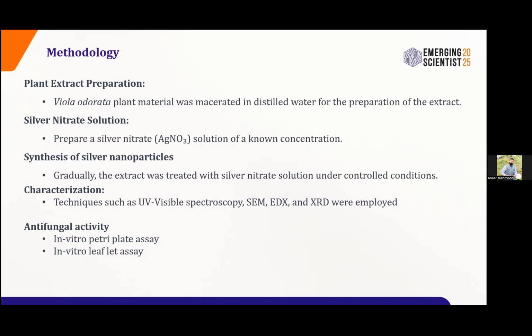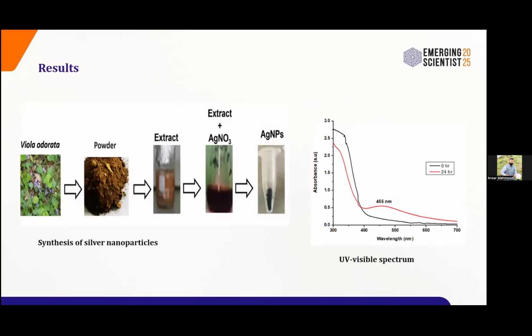The methodology I adopted for this research, first of all, was the plant extract preparation. The plant used for the preparation of nanoparticles was Viola odorata. The whole plant was ground into powder and an extract was made using distilled water, and then nanoparticles were synthesized by mixing the plant extract with silver nitrate solution under optimum conditions. They were characterized using different techniques like UV-visible spectroscopy, SEM, EDX, and XRD. And then antifungal activity was assessed through in vitro petri plate assay and in vitro leaflet assay using leaves of the plants. So here are the results.